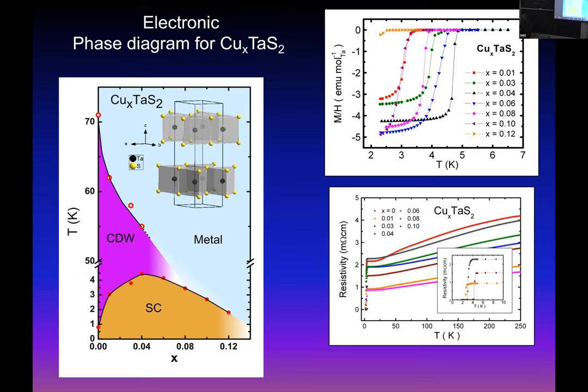This is just how you measure the superconductivity. So superconductivity has a variety of different features. One is that it expels magnetic fields, which you saw the Sumo Wrestler standing on superconductors. So we can measure that. That's from the one corner there. And then, of course, the characteristic of a superconductor is that the resistance drops to zero. That turns out to not be such a good measure because you can't really tell me where zero actually is. But this flux expulsion, you can actually measure pretty easily. So we measure that.